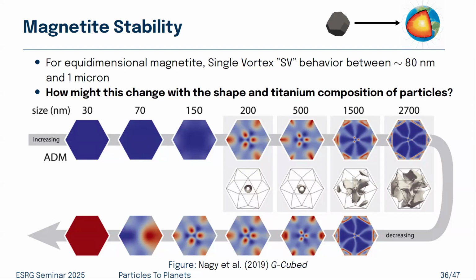And that could be, as I said, with that sort of multi-axial versus uniaxial thing, when you've got multiple different states competing with one another, this is an idea that potentially something there will behave poorly in our paleointensity experiment. So in this region at the start of your single domain to single vortex transition. So in summary, above about 70, 80, you get single vortex, and then above about a micron you get multi-domain, right? That's kind of our regime that I showed you before, that classic regime.